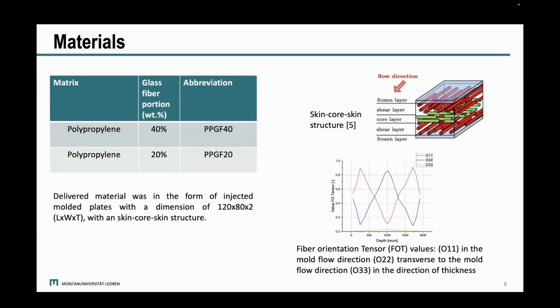It means that on both sides of the plates, we have fibers which are highly oriented in the mold flow direction. And in the middle of the plates, we have mostly the fibers which are oriented perpendicular to the mold flow direction. On this curve, you can see the fiber orientation distribution in the direction of thickness. As I mentioned, we have two skin layers on both sides of the plates, and in the middle we have a core layer. Also, the red line shows the fibers which are oriented in the mold flow direction, and the blue curve shows the fibers which are perpendicular to the mold flow direction.